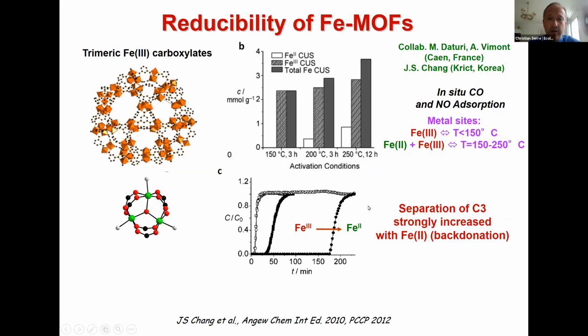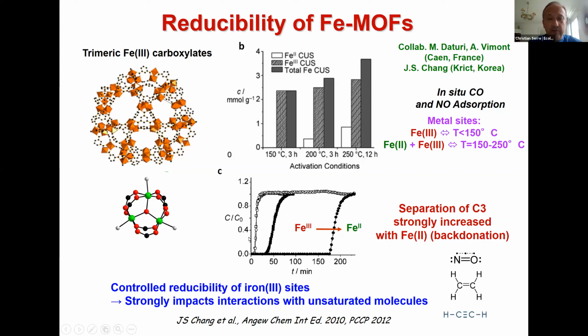And here, as a model utilization of this property, some colleagues from Korea investigated the separation of olefin using the pure iron 3 MOF. In this case, you have a low selectivity, around 5 to 6. But as soon as you have some additional iron 2 sites, the selectivity increases drastically. Of course, this is not suitable for real application, but later on, people like Jeff Long, for instance, used the pure iron 2 MOF 74, and showed that they could have outstanding olefin separation ability. So these additional iron 2 sites bring additional interaction with a large number of unsaturated molecules.